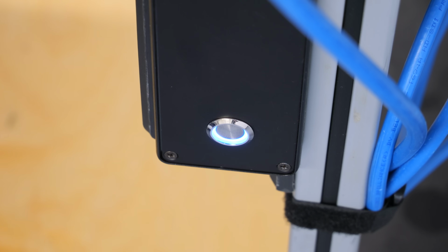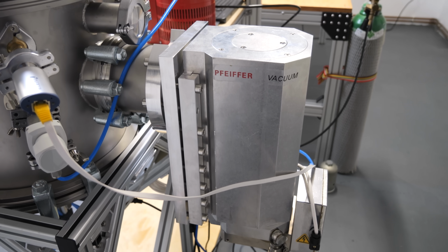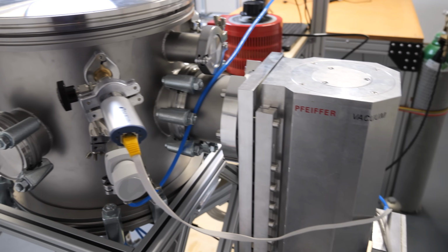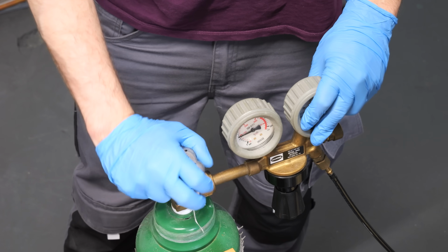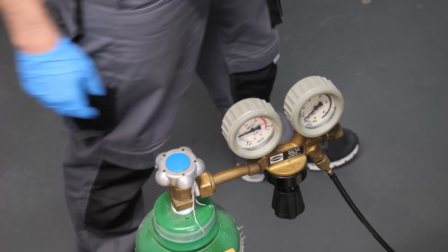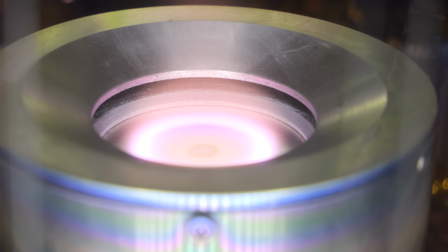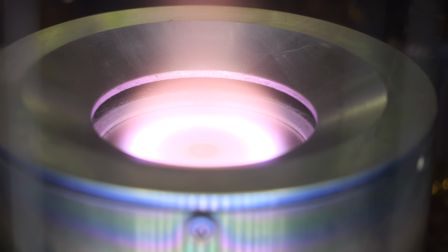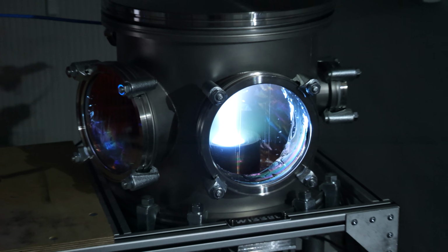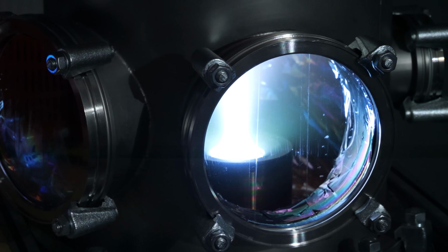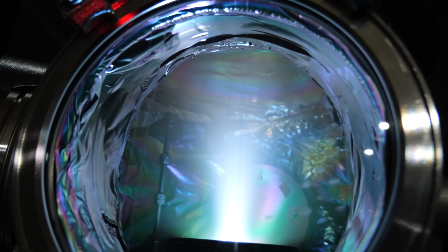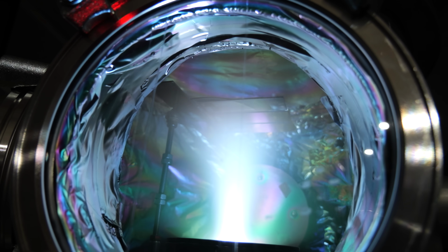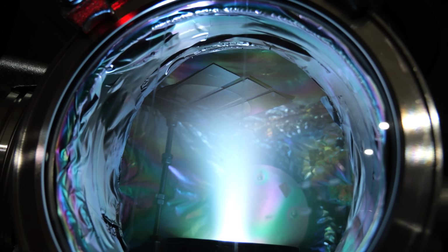After sealing the chamber, I start my rotary vane pump, followed by the turbomolecular pump. By introducing argon into the chamber, I achieve a pressure of approximately 1 × 10 to the power of -2 millibars. When I apply a voltage to the magnetron, you can see the plasma. In this plasma, argon ions knock titanium atoms out of the target, which then deposit onto the slides. If you look closely, you can see how the glass loses its transparency and slowly develops a reflective surface.